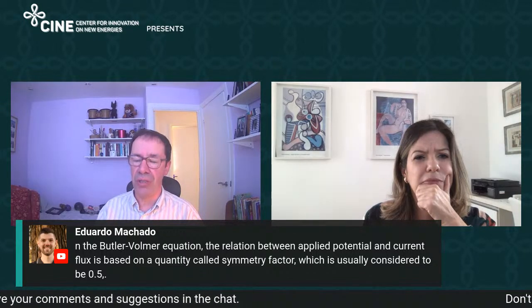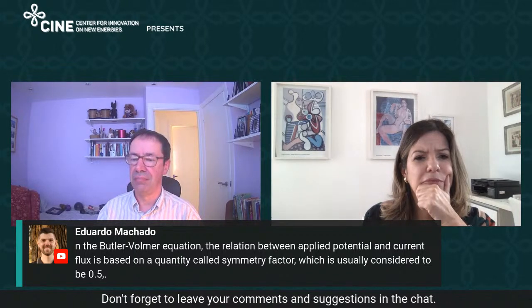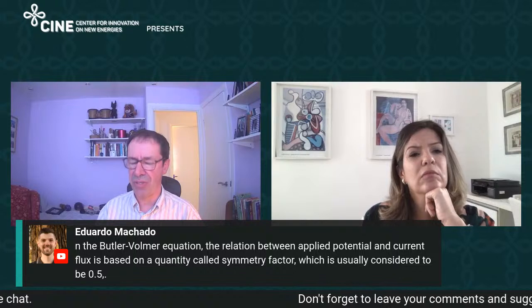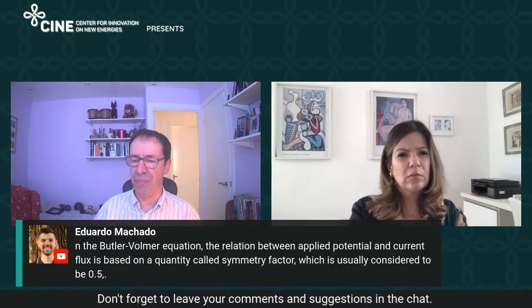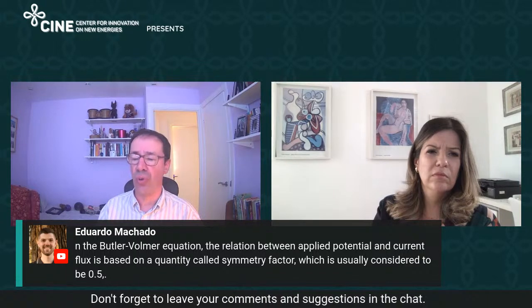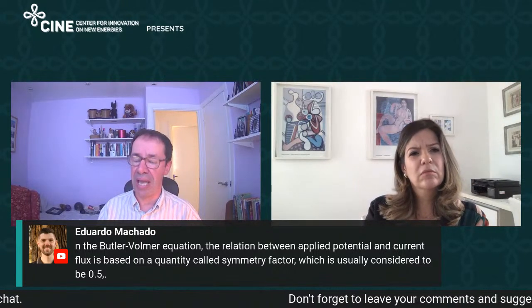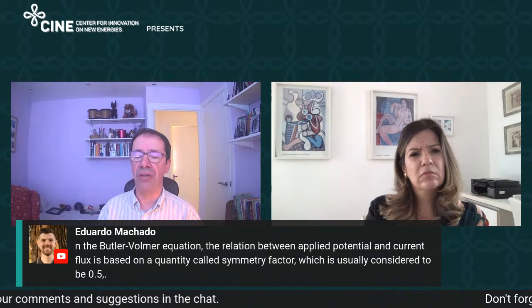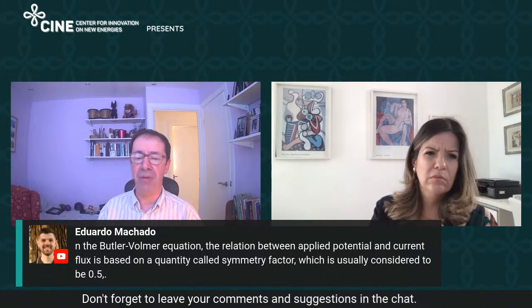The analysis we are using assumes that as you change the potential, there is no change in activation barrier. The evidence for that is that as we change the potential, the rate constant doesn't change in our measurements. Now, that is bound not to be generally true. The analysis we are doing is, if you like, the extreme of assuming that we only have to think about population and not at all about changes in activation barrier. So far, it's worked quite well to analyze the data we have on the materials we've studied under the conditions we've studied. How generally relevant it is, and at what point we have to consider both changes in population and changes in activation barrier, I think will depend upon the conditions we use.